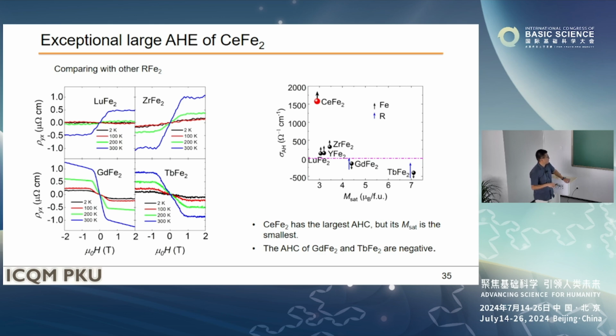These two are ferromagnetic. So the anomalous Hall effect signal is reversed because your iron moment is inverse, right? The interesting thing happens here. If I plot the saturation magnetization on the x-axis and the anomalous conductivity on the y-axis, you notice this cerium has the largest anomalous conductivity, right? But the smallest saturation magnetization. Very interesting. So what's going on?